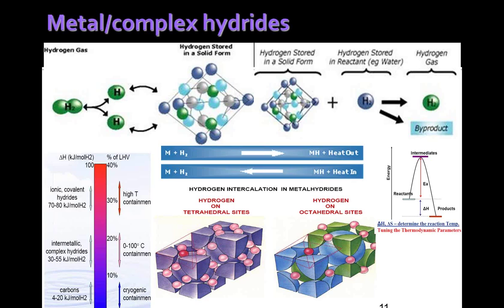of material. And on the other side, on your right hand side, the plot shows the energy with respect to delta H. So, for example, if we're going from the reactant side and getting to the product side, there's a huge thermodynamic barrier, which causes many of the hydrogen storage materials not to function very efficiently because of the thermodynamics. So EA is activation energy, delta H is enthalpy of reaction.